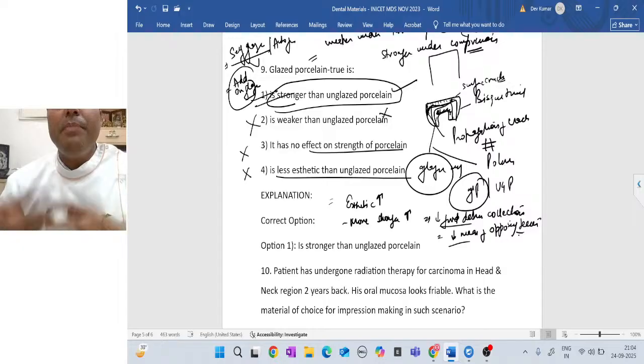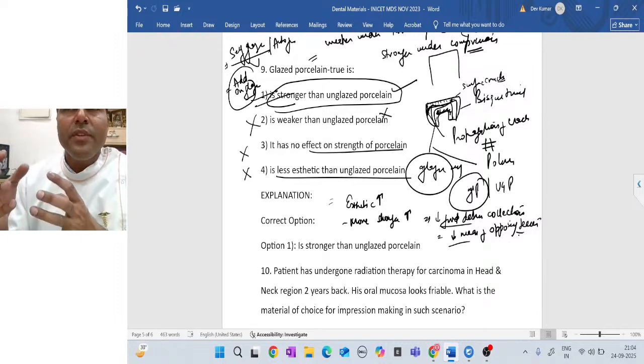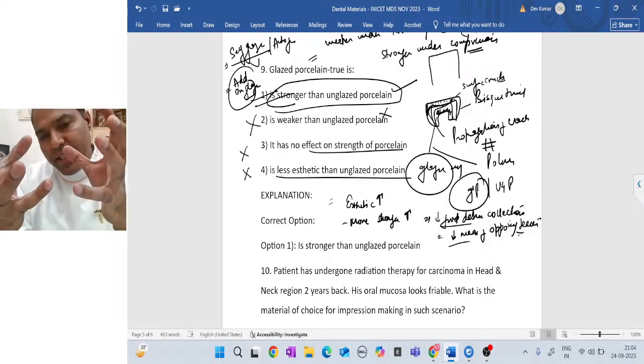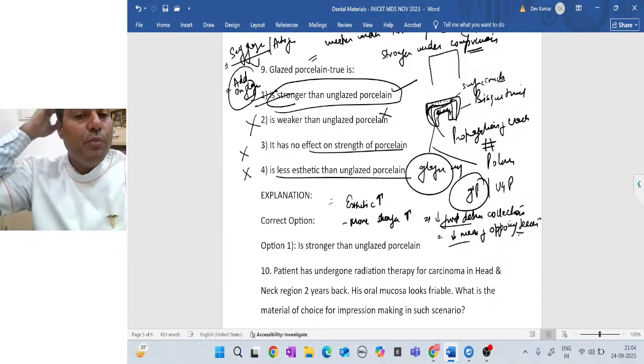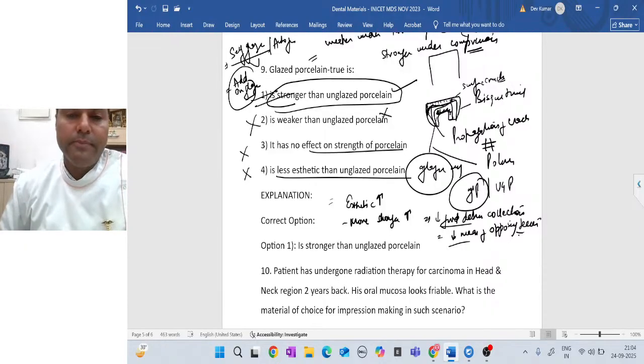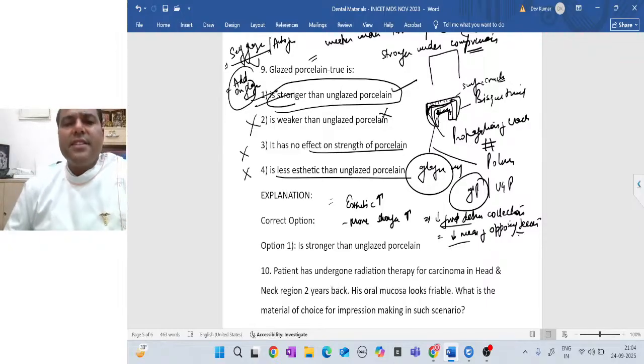So during buildup of the porcelain layers, for example dentine body, the enamel, we have to put the vacuum on. We want the particle to come closer. So during normal cycles the vacuum of this furnace is kept on. But once we are doing glazing, because everything has been done, I just give a glazing cycle.